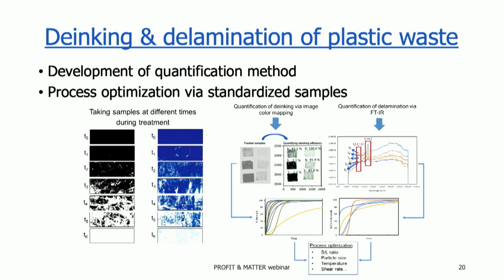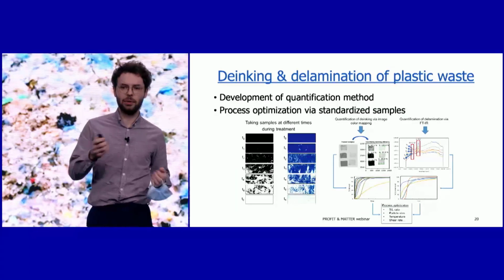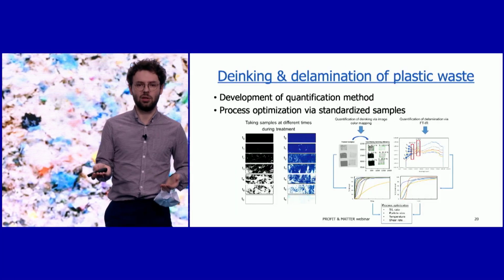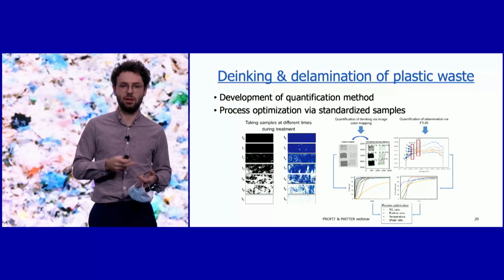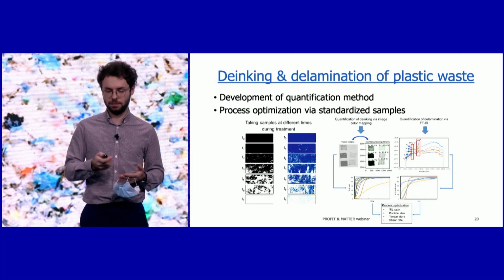As a next step, we optimized this method, and for this we first developed a method to quantify both the de-inking efficiency and the delamination efficiency. The method to quantify the de-inking efficiency is based on color mapping, and the method for the delamination efficiency is based on an FTIR analysis. As such, we were able to optimize our process in terms of solid-liquid ratio, shear rate, temperature, and so on.